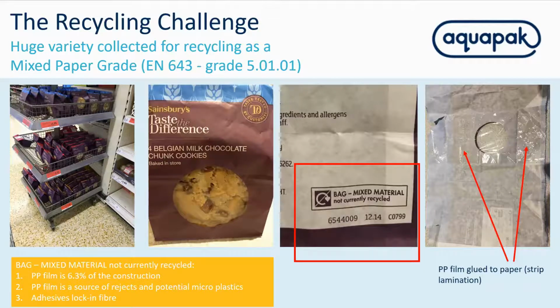The other interesting point is adhesives, of course, are also a key part of this in terms of what you use. Adhesives are there to obviously adhere the material, but by doing so, they can lock in fibre. And the choice of adhesives is key here. We're about to produce a white technical paper where we did a complete review in combination with DS Smith of looking at different adhesive types and their effect on fibre retention and fibre recovery. And it is quite interesting because it's often a forgotten part of the technology here in terms of what you may wish to combine in a laminate or even an extrusion coating.